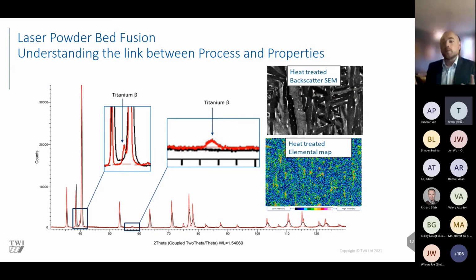Now, Ti64 is a two-phase material. It's got an alpha phase and a beta phase. One gives us good strength, one gives us good ductility. And getting the right balance is really important. But getting the right balance usually requires not cooling nearly as fast as AM.